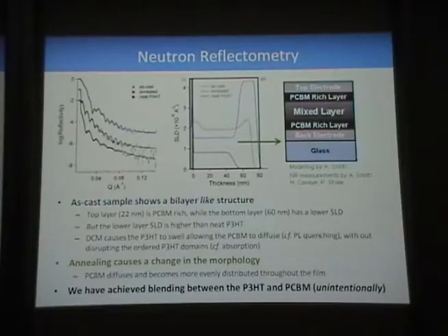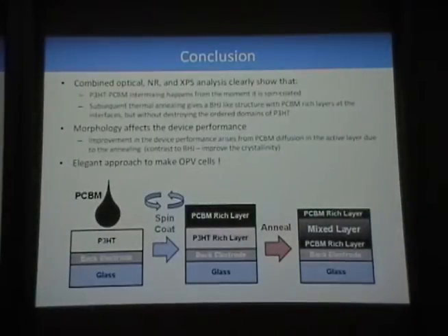So this cartoon here shows what's really happening. Basically you have a PCBM-rich layer at the interfaces and a mixed layer of P3HT and PCBM. So in a sense, we've achieved blending between the P3HT and PCBM unintentionally. I mean, that wasn't the reason why we did the annealing. So in conclusion, the combined optical, neutron and X-ray analysis clearly show that the P3HT PCBM intermixes from the moment when you spin coat.